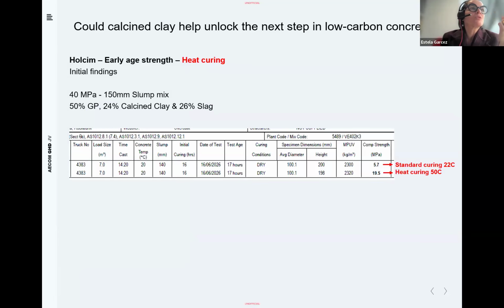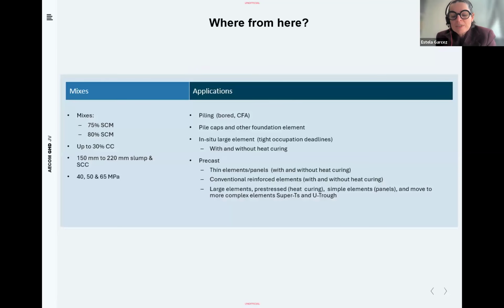Further to that, Holcim started doing some heat curing tests, and again, after 17 hours, we can see here that using heat curing of 50 Celsius, we have that 19.5 MPa that gives us that kind of evidence that the early strength, that is critical for both pre-stressed and tight occupations, can be solved. So of course there is more that has to be done for us to crack those most challenging applications, I would say.